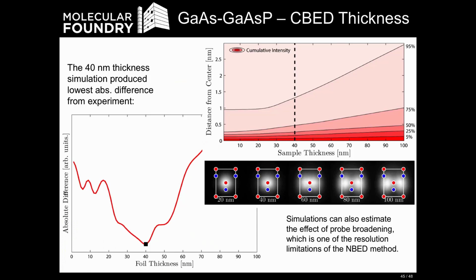So we would estimate that our spatial resolution of the strain field is probably about half a nanometer, somewhere between half a nanometer and 1 nanometer, because we can estimate the thickness of our sample with high precision here. So once again, a single data set collection, but multiple experiments performed after the fact. And that's the real power here of this method.